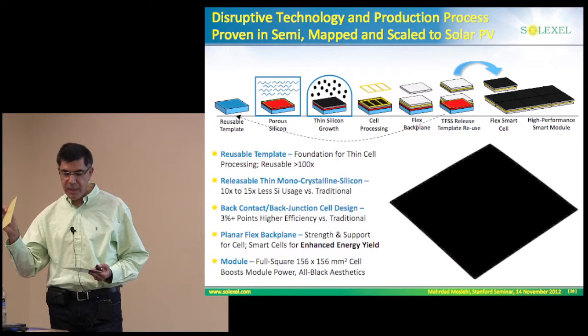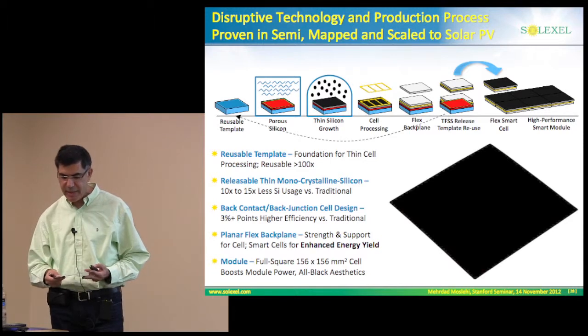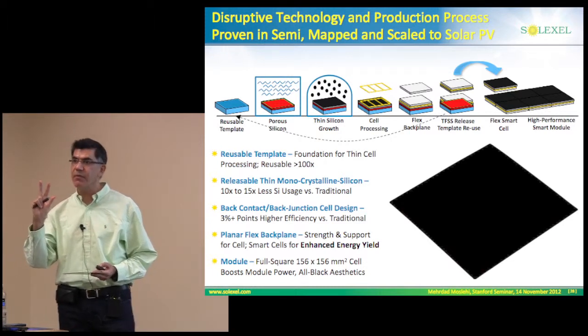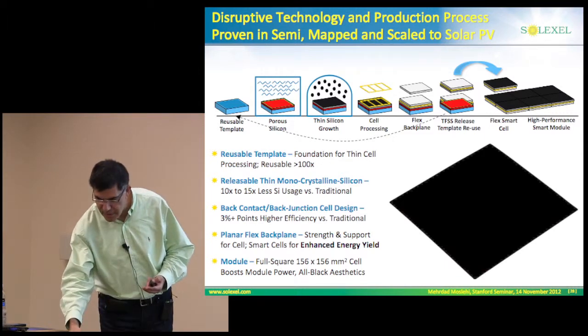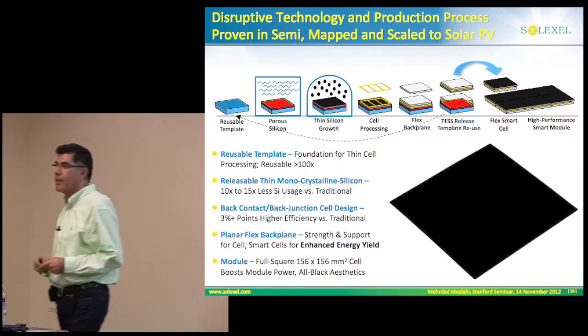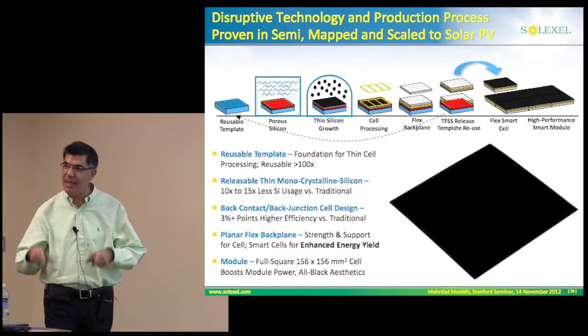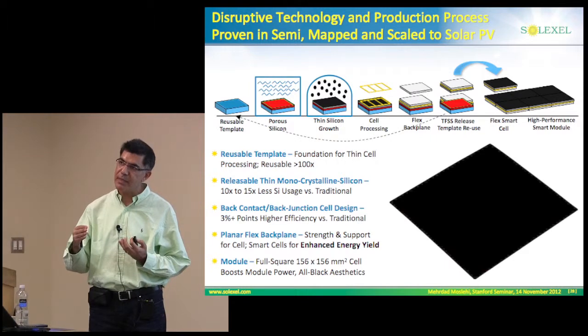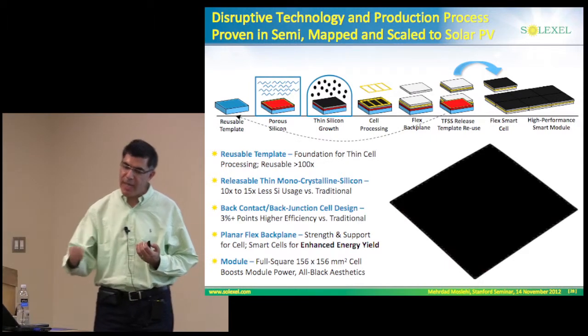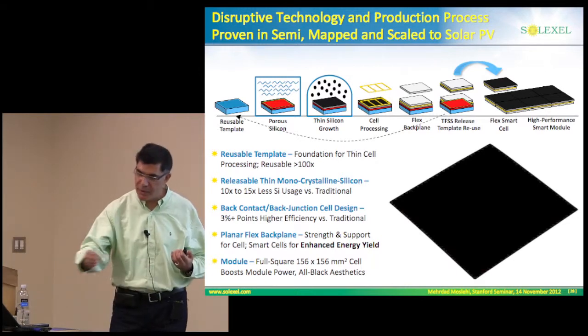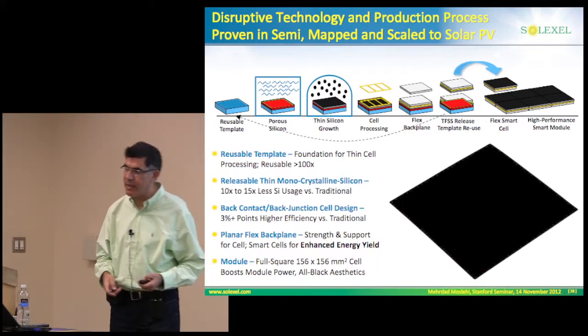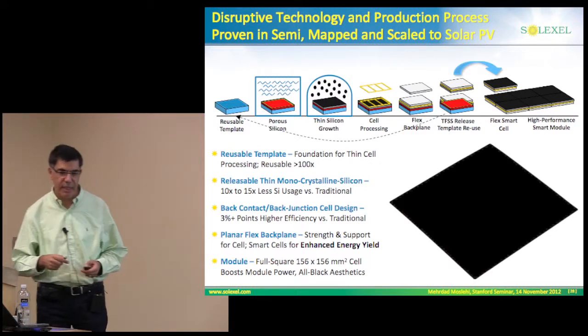Then we use a very inexpensive polymeric sheet. It's a 100 micron sheet that is laminated on the process cell. And then we define the release boundary with laser, and it's simply a lift-off release. So by the way, this is the world's largest area liftoff, and we do that instantaneously on demand. The important thing about this liftoff process is to make sure that you can lift off on demand and not prematurely as you do the process.